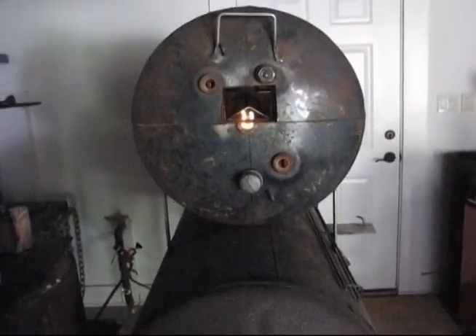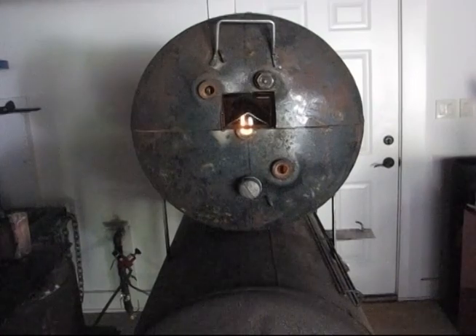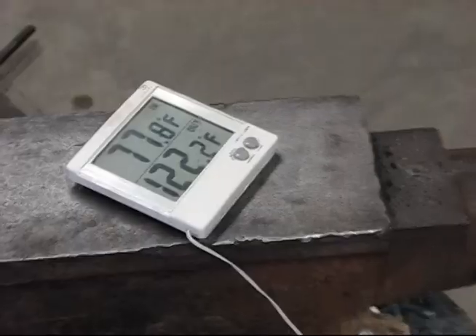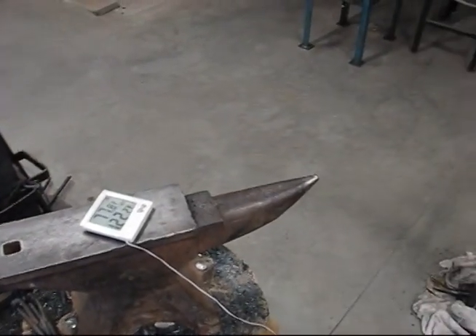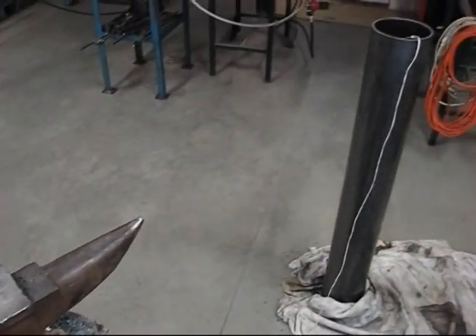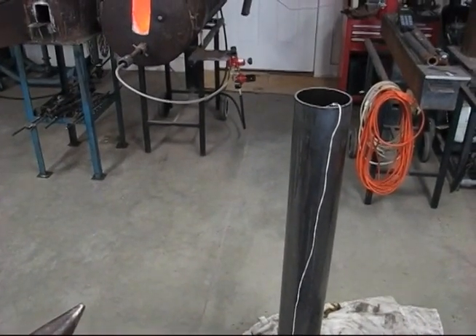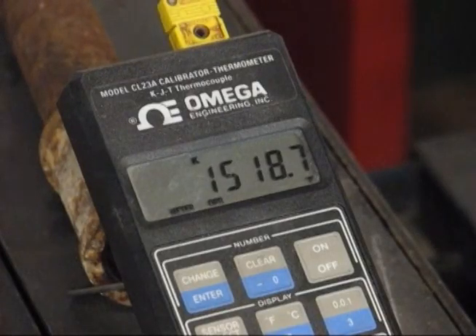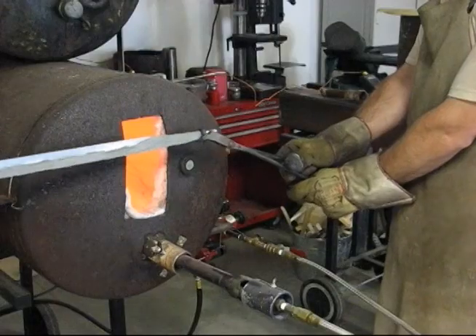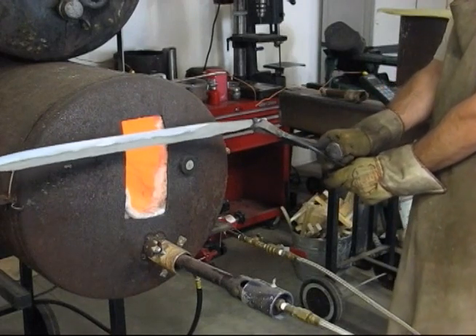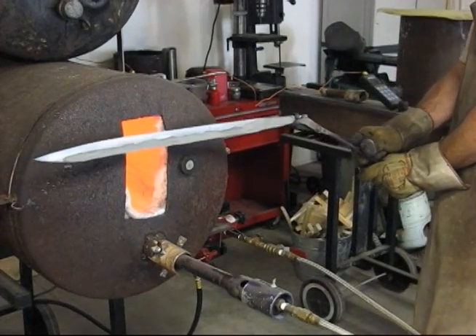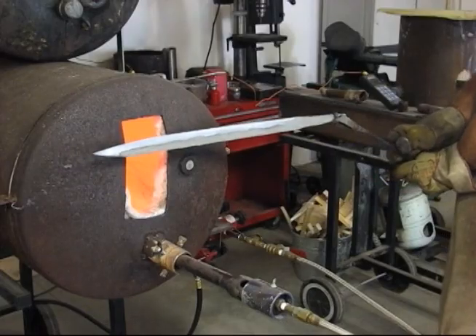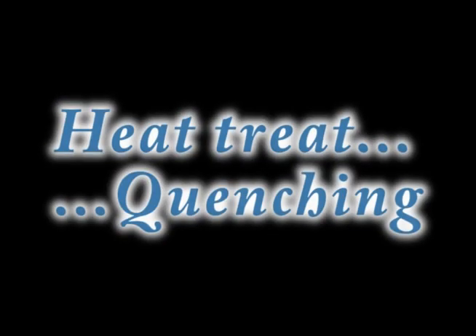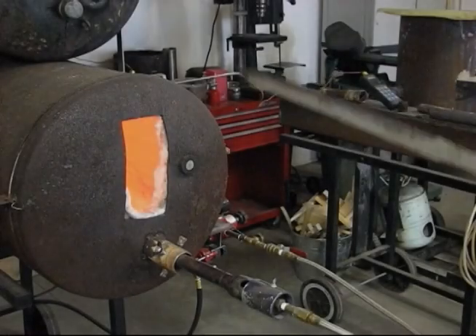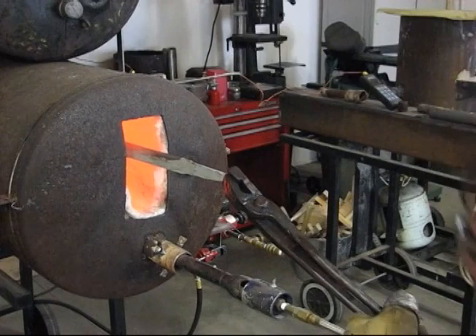While the clay dries up fully, the heat treating oven, the tempering oven, and the oil for the quench are brought to operating temperatures. The blade is placed in the oven and allowed to reach critical temperature.